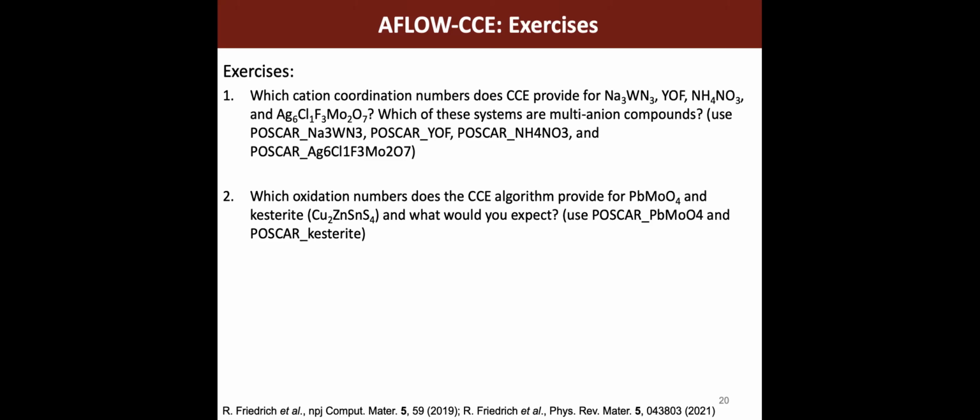If you're referring to the oxidation states, you might get from a DFT level when you do Bader charge analysis, this is what I would think you're referring to, you might get more reliable oxidation numbers when you use DFT plus U instead of DFT. We did not need to resort to that because with the Allen electronegativities, you get this basically for free. We have also implemented this for oxides on the Bader charges, but the Bader charge analysis is much less reliable than this. Just let me see.